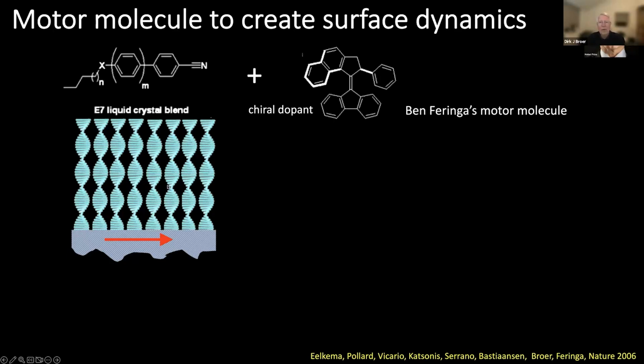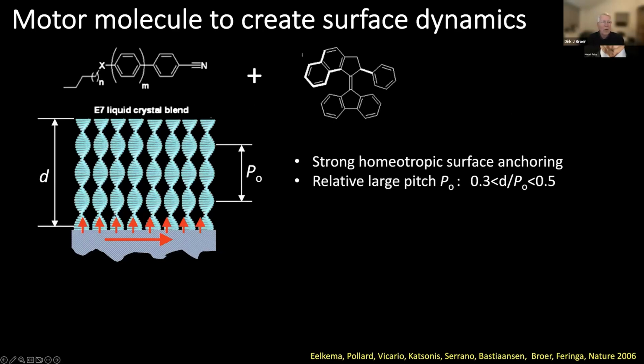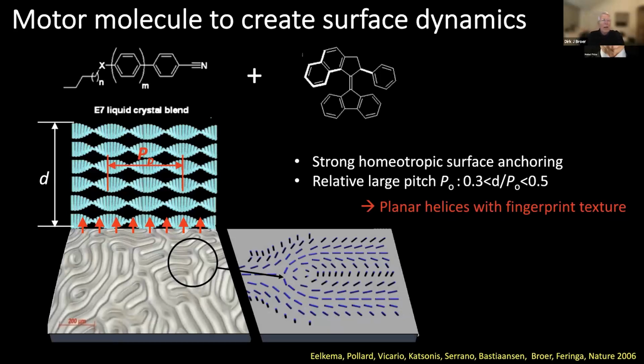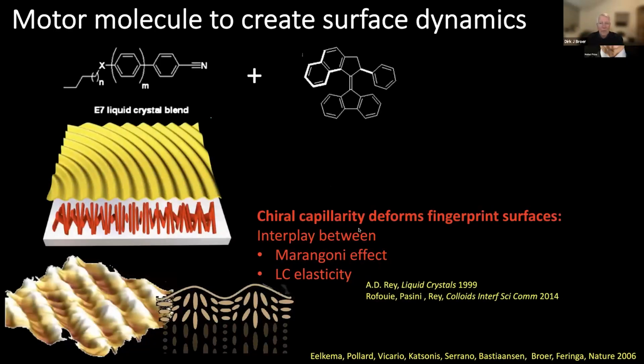Well, this is the lowest energy state, but if you add some energy to it by a very strong anchoring surface at the glass substrate in this case, then you control the ratio between the thickness of the film and the pitch of this helix, then you can bring these helices into a planar orientation, and this planar orientation we call the so-called fingerprint alignment, because they find their way in an organization which looks very much like our human fingerprint in this case.